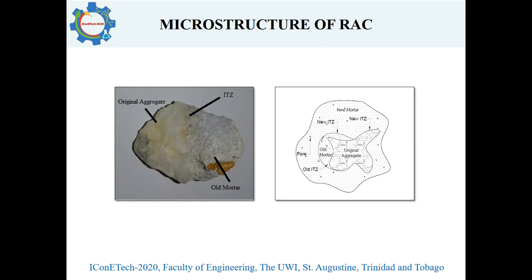On the other hand, the image on the right shows a typical cross section of the recycled aggregate concrete. When the recycled concrete aggregate is placed in a new concrete matrix, a new mortar layer surrounds the recycled concrete aggregate. Together with this, a new ITZ forms, which is an additional weak zone. Due to the inferior properties of the recycled material, this negatively affects the mechanical and durability properties of the recycled aggregate concrete.